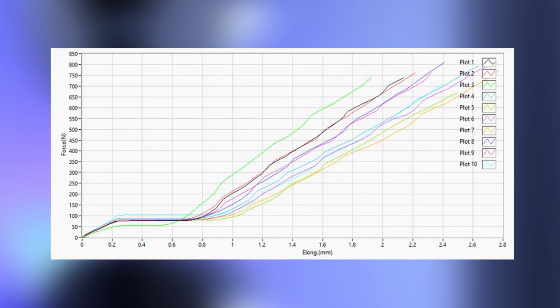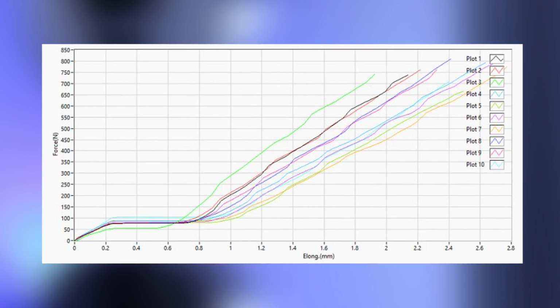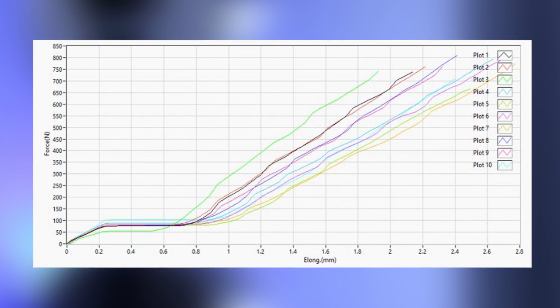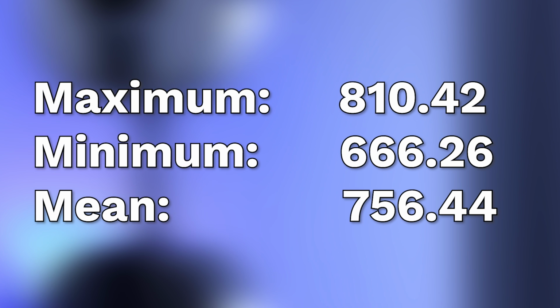Ooh, doggy, that was a little bit worse. With the Polyterra Matte Black, we ended up with a maximum force of 756 average across all the tests. And it was actually a pretty tight test. There was not a lot of variation. Sometimes we see a big old spread of data with these tests. It went over about 100 newtons back and forth, which is right within what we would expect from the variation of just 3D printing in general.